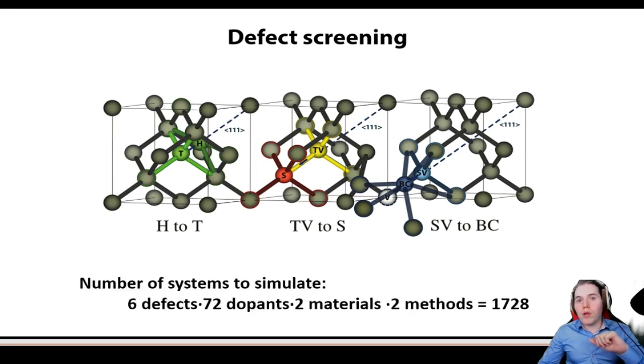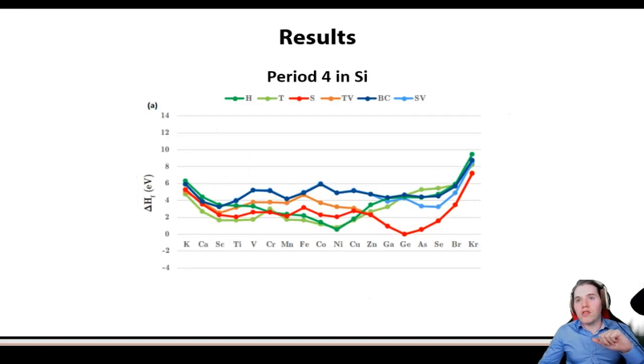If you look at these different defects, if you put 72 different elements on these 6 possible positions, you get quite a lot of combinations. It is actually for 2 materials using 2 methods, and that was about 1700 calculations. Now, if you look at the results, look for instance at the red curve, which is how much energy it costs to replace an atom in silicon with these other atoms that you see here on this axis.